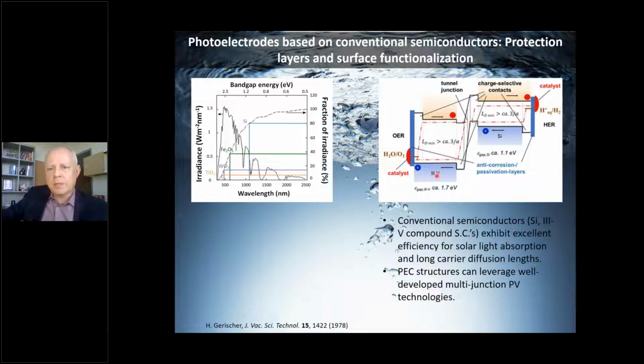So what's pictured here is a schematic of the band gaps, the electronic structure and energy band diagrams of two different semiconductor materials, a III-V material with a band gap of around 1.7 eV, and silicon, which has a band gap of 1.1 eV, and how these can be coupled together by providing a tunnel junction between the two semiconductors, and then decorating the surfaces of the semiconductors with appropriate catalysts to bring electrons to the right side here for reduction of protons to make hydrogen, and holes to the left-hand side for oxygen evolution through the electrochemical splitting of water.